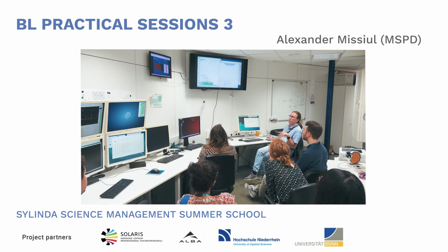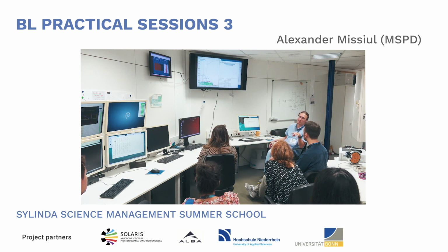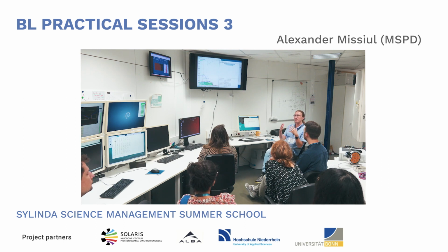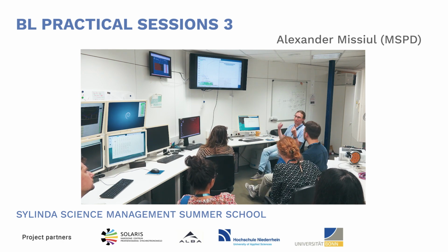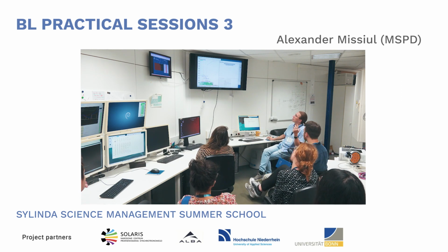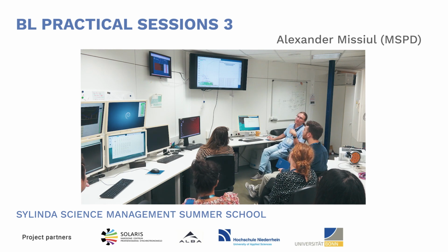And the next step of structure solution is search for the real symmetry of our structure. So normally it is done using so-called systematic absences. So the positions of the peaks where the peak should exist, but the intensity is 0 because of the symmetry of the crystal. So again, the program can do it for us, but otherwise you would have to go to the so-called International Tables for Crystallography and do a manual search. I hope you will not do this.